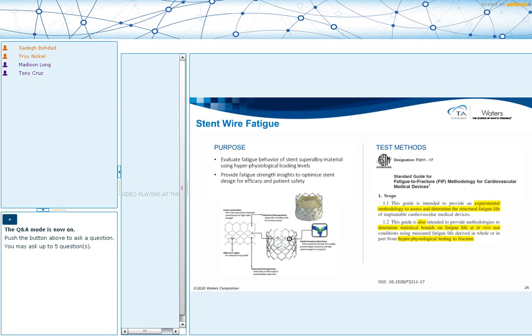When we are discussing fatigue behavior of the material, there are two paradigms. One is fatigue to failure, meaning that you will test your material until it breaks, and the other would be fatigue to success, meaning that we only test to a number of cycles to show that this material can withstand that many number of cycles. Usually, the first one, the fatigue to failure, is used to establish design curves for the second one, for fatigue to success. And it's important to measure a statistically valid number of samples to do that.